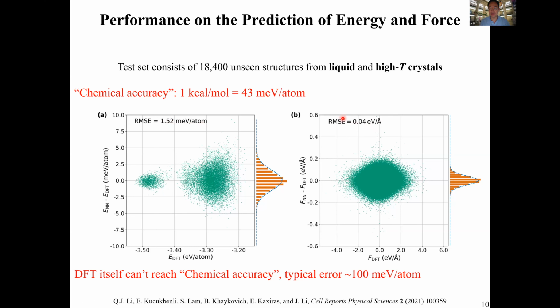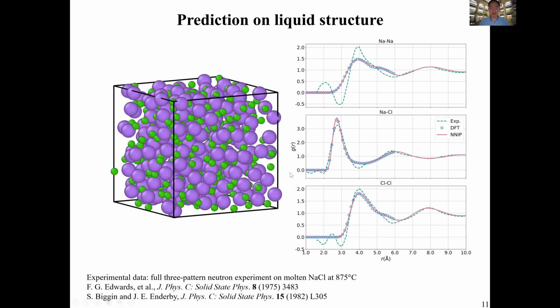And the force error is 0.04 electron volt per angstrom. I just want to say that we are able to fit DFT much better than DFT can represent reality, because DFT is known to have above chemical accuracy error, typically 2 chemical accuracies, like 100 meV per atom. So as far as the goal of the machine learning potential, this fulfilled the target.